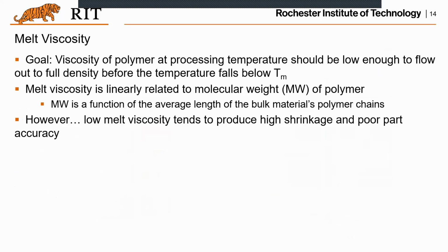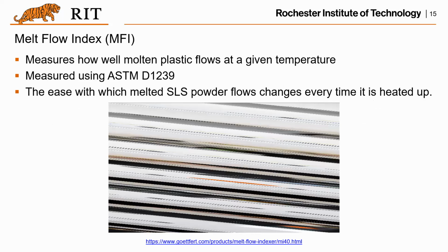Another one is the melt viscosity. After the material is heated up, it becomes a liquid state, and the viscosity of the polymer should be low enough to flow out to a full density before the temperature falls below the melting point. So that is related to the material itself, and low melt viscosity tends to produce a high shrinkage, and essentially it will cause a low part accuracy.